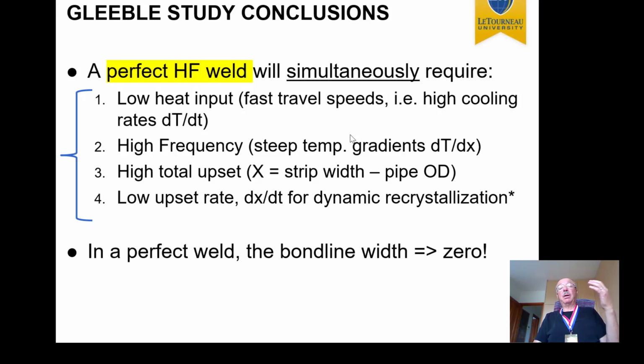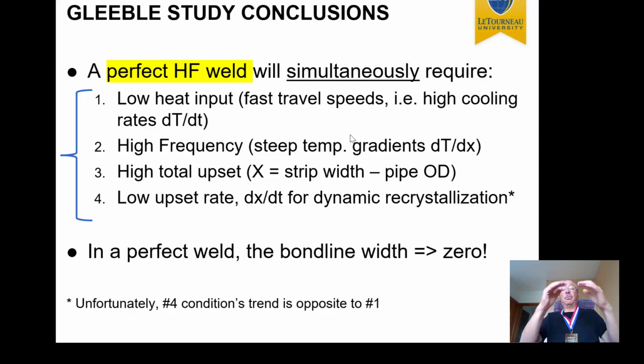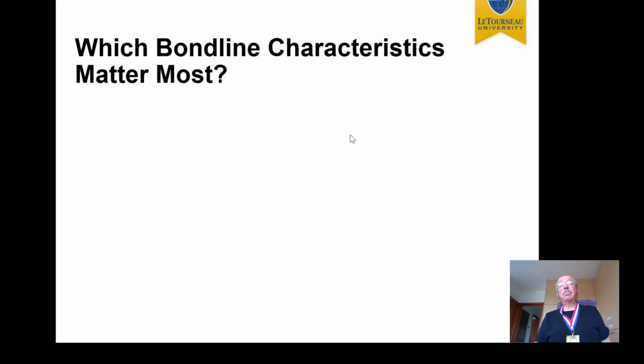Like in a perfect weld, the bond line width would be 0. But again, unfortunately, condition number 4 is opposite to number 1, that you'd like to weld really fast, but deform slowly. So that's why you see variations within systems and powers and all that, because all this has to be simultaneously accomplished, which is very, very hard. So that was really basically what we concluded.